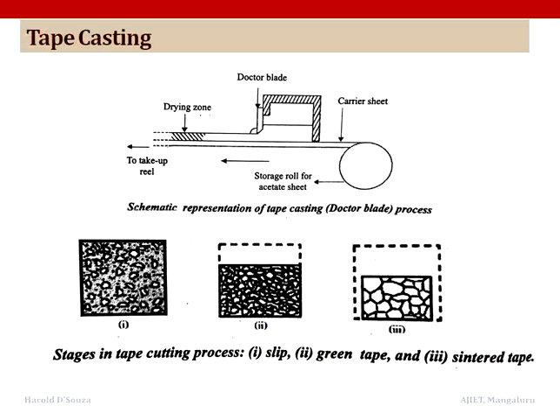Tape casting. Tape casting, the process that is schematically shown in the figure, is a variation of the slurry casting process and it is used to produce thin flat sheets. This process is also called the doctor blade process. We have three major steps and they are the formulation of the metal or ceramic slurry, casting, drying and firing. Now this process consists of preparing a dispersion of the metal or a ceramic powder in a suitable solvent with addition of a dispersing agent to improve the dispersion of particles. Now after a satisfactory dispersion is achieved, a binder is added and the whole mixture is fed into the reservoir.